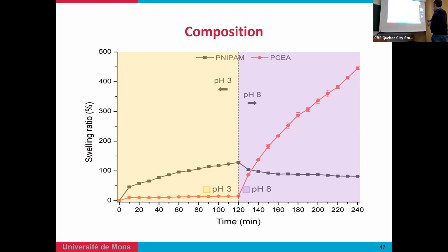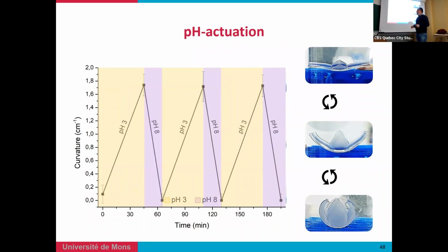But in the case of the acrylic, you can see that when you add a certain base, placing it in alkaline conditions, the swelling ratio increases a lot because of the ionization of the acrylic moieties. Based on that, we were able to show, by playing with the pH, passing from acid to basic, this actuation shown in this figure.